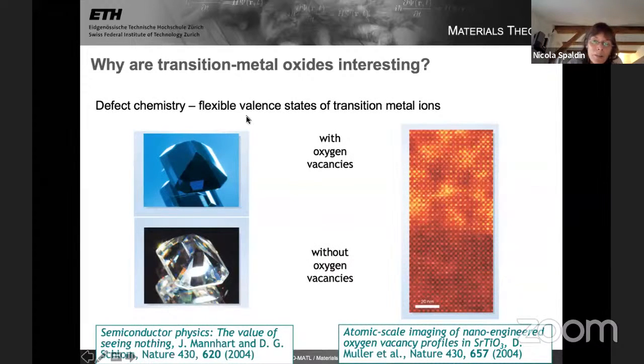And then I think this is the last point I wanted to make about why transition metal oxides are so interesting. And that's that we know that block of transition metal ions can adopt many valence states. For example, it's common to have iron 2+, iron 3+, it's even possible to get iron 4+, and so on. And because the valence states of the transition metal ions are so flexible, the defect chemistry is very rich. For example, we can take out an oxygen and the oxygen will leave its electrons behind. And that's not a very energetically expensive process because the transition metal can readily change its oxidation state. So the defect chemistry can be very rich.